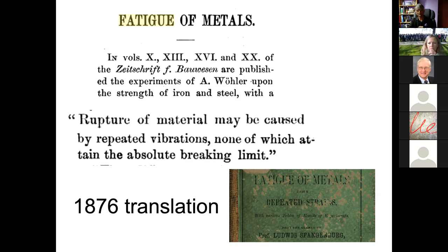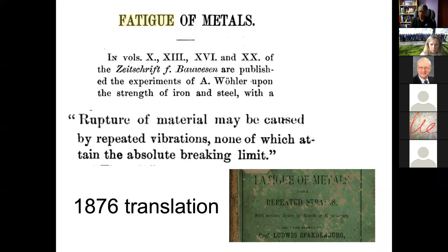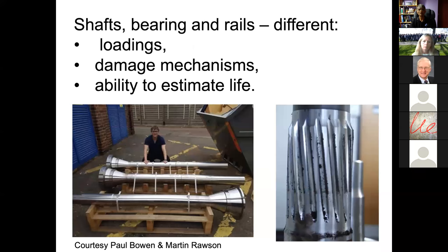One difficulty is that you have to assign a life to components. You do a lot of fatigue testing and work out the probability of failure. In the context of bearings, you have the L-90 life or L-10 life, where you expect 10% of the bearings to fail after a particular time period. The ability to predict failure is extremely important because it determines the life of complicated engineering components.